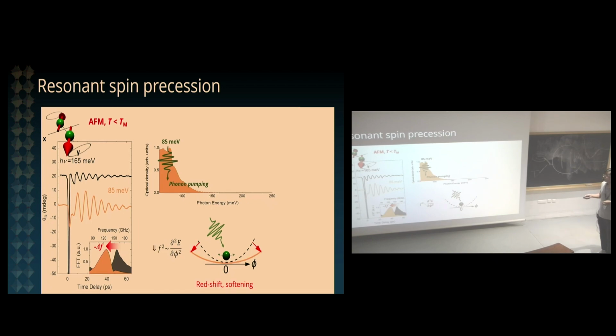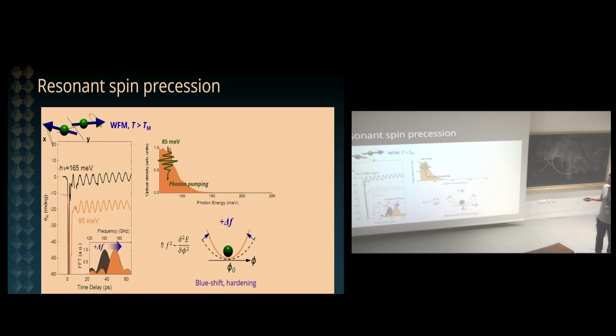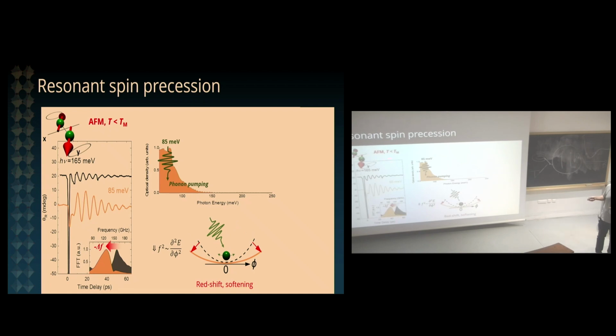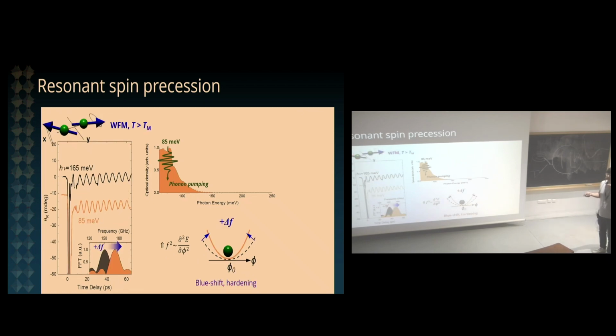So this is directly telling us that we are softening the magnetic potential by exciting the phonons. You can do the same experiment. This is measured in the low temperature collinear antiferromagnetic state. You can do the very same experiment in the high temperature phase where your system has this weakly ferromagnetic state.